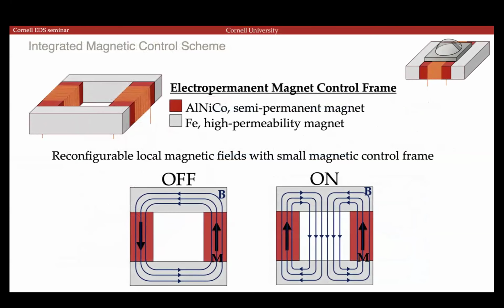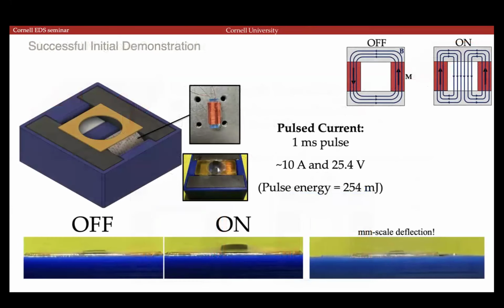And then I think we'll skip this one as well. We also made a control frame. If the magnetizations in the two regions on the left and right are magnetized anti-parallel to each other, and the sample is placed in the middle, then the sample experiences no magnetic field. But when you flip one of the magnetizations just by applying a current to it, then these anti-parallel magnetization sections produce a field that is forced to return through the center region. And this is a demo that my student produced a few weeks ago, where you can see the large deflection when that same magnetization is switched, and the sample on top is either in the on or off state.